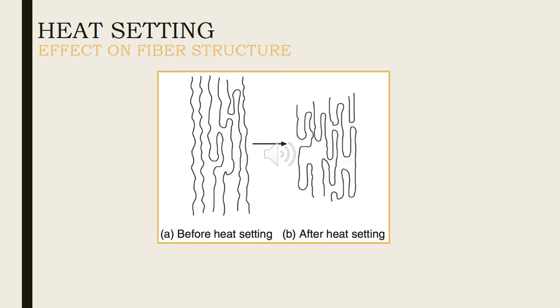Heat setting determines the morphology and dimensional stability of thermoplastic fibers. It includes three fundamental factors: temperature, time, and speed. In practice, temperature should be set greater than the secondary transition temperature and below the melting temperature.